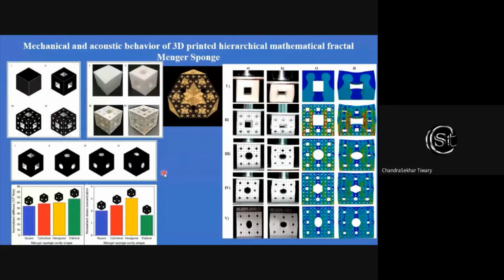Recently, we just published this paper where we use a mathematical based model to build the structures, which is called Menger sponge. They are porous, but they have certain periodicity. When we change the shape of this porosity or these individual holes, we can clearly engineer the mechanical properties or energy absorption. We do a deformation of these structures and try to understand the role of this porosity or this topology, and try to compare with FEM and explain the whole idea.